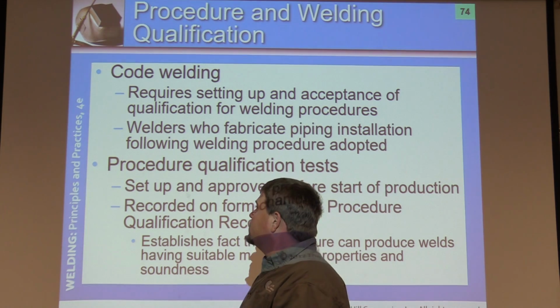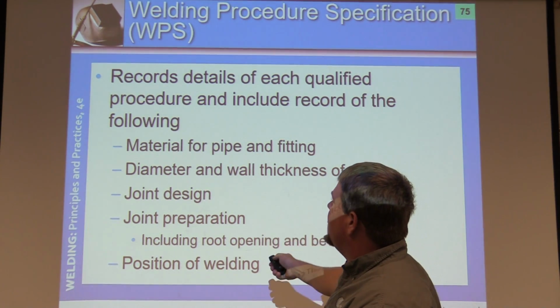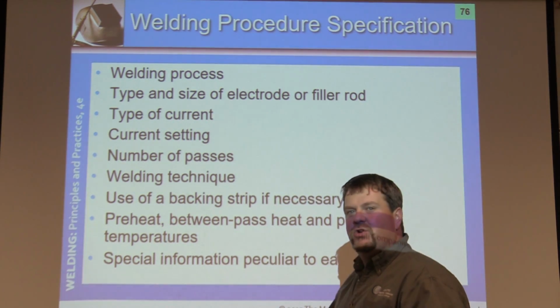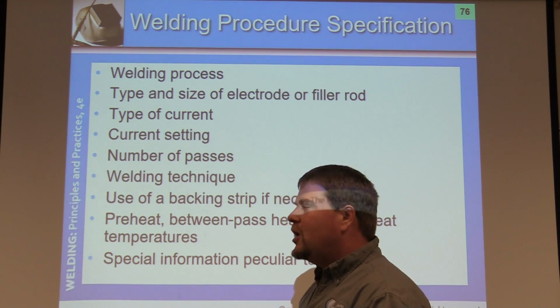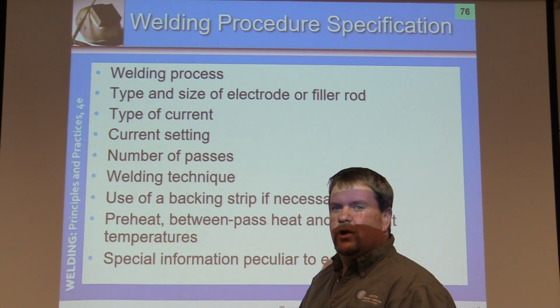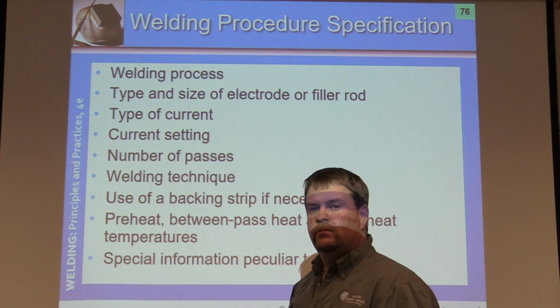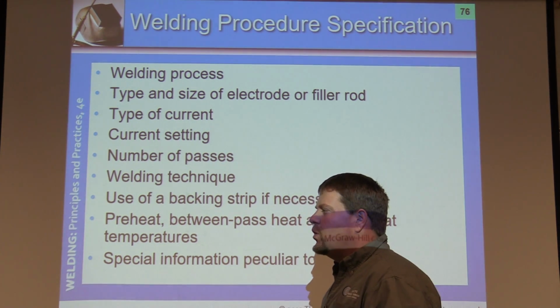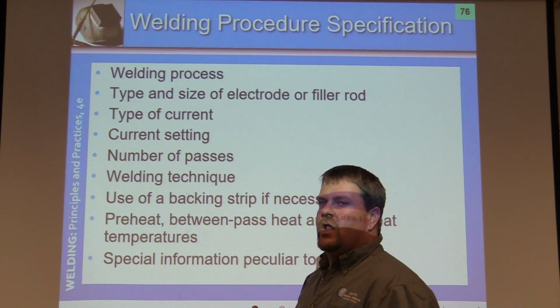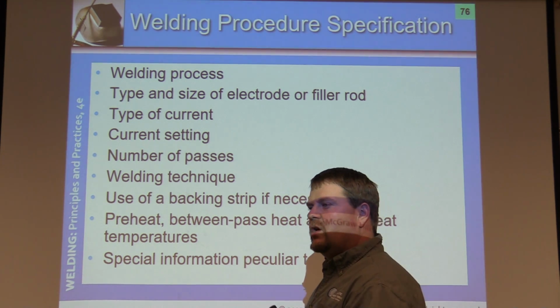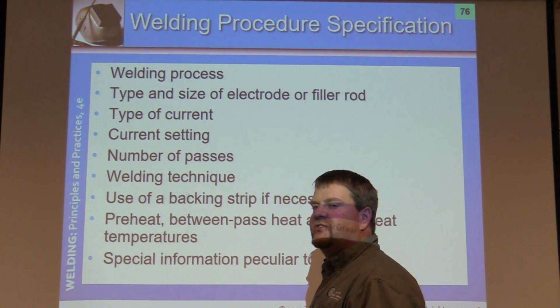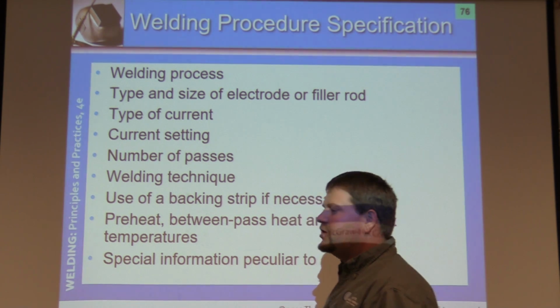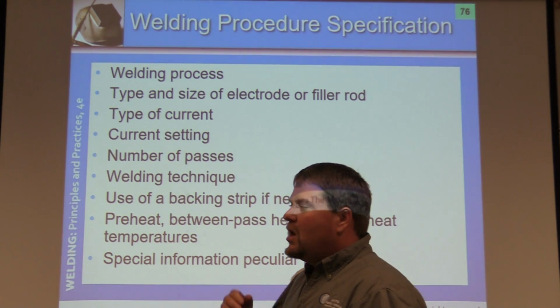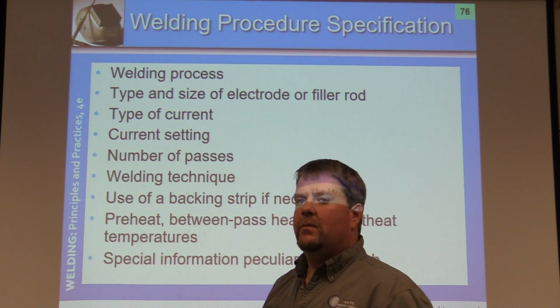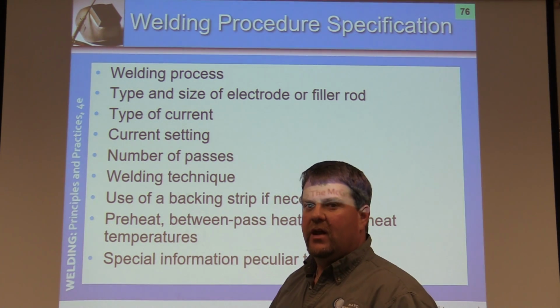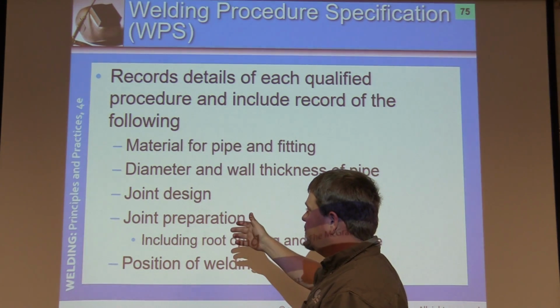Okay? So I'm going to follow every one of these variables right here in this procedure. I'm going to make sure that the welder's doing it, or I'm going to do it. Make sure everything aligns. I'm going to record it. I'm going to time you. You weld one welding rod. You're going to start welding. I'm going to start the stopwatch. You're going to weld, say, 4.5 inches in 45 seconds. I stop the stopwatch. I measure how far your weld is. I'm going to put that in. We're going to calculate the heat input. I have to record that and put that in the values of the procedure qualification record.